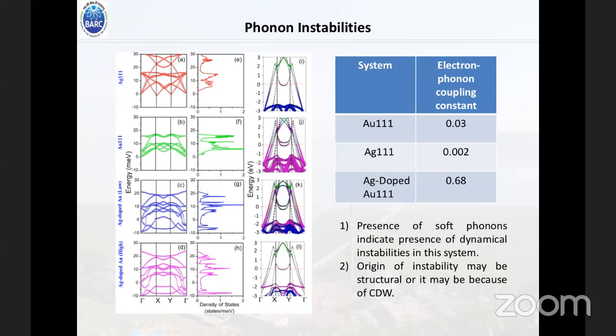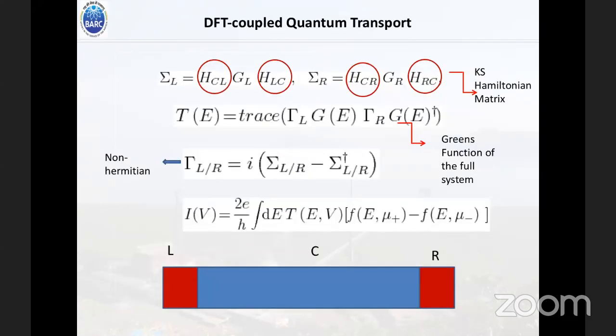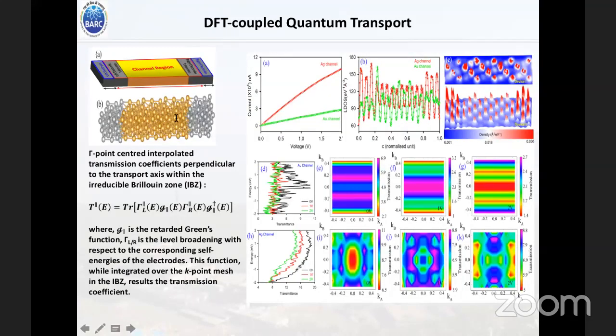Now, next is our DFT coupled quantum transport. I am not describing it here, but what we can show here is that even for the simplest possible device, that is Ag channel and Au contact, and the reverse, Au channel and Ag contact, for those kinds of systems we have calculated the IV characteristics and also the local density of states. If you look at the local density of states of this system, this is the one-dimensional local density of states, that will be showing you that near the interfacial region for the Ag channel system, there is a large interfacial scattering present.